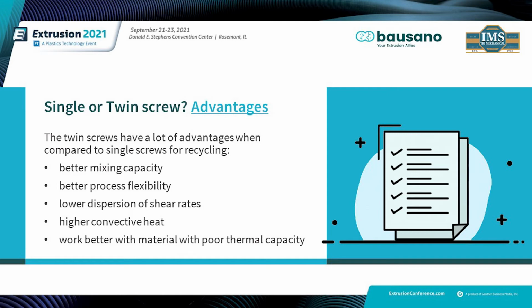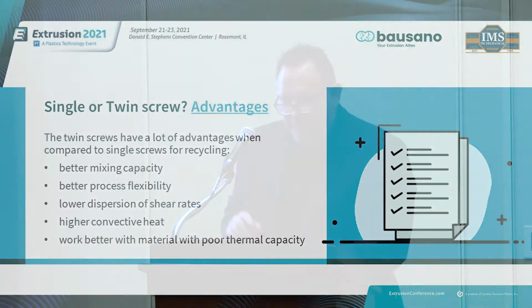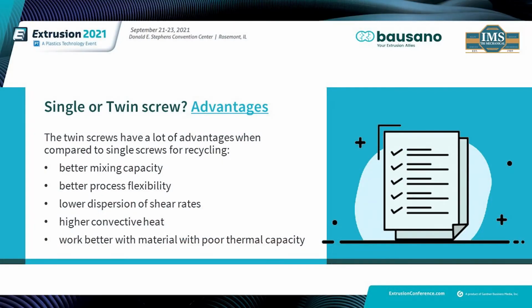They are typically long and have segmented barrels, and the screws are sectioned to match the barrel, so you can alternate sections of mixing and conveying of the material, venting and adding filler or other components. Twin screws work better with material displaying poor thermal capacity as well, resulting in advantages while processing polyolefin or PVC that degrade and become more unstable with multiple extrusion cycles. Twin screws have a lot of advantages when compared to single screw extruders for recycling, beyond mixing capacity, including a better process flexibility.